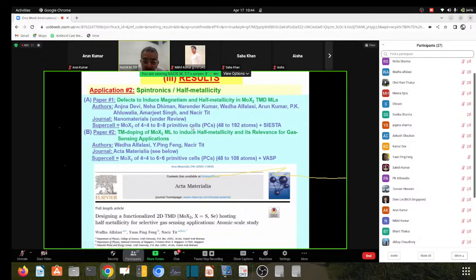Here they use supercells of size 4x4 to 8x8 primitive cells, consisting of 48 to 192 atoms. The good thing with transition metal dichalcogenides is that you have only one metal layer, which means this is computationally less costly than the mixing. Here they use SIESTA basically, but my student Watha contributed using VASP, and we focused on the half metallicity to sharpen the paper more.